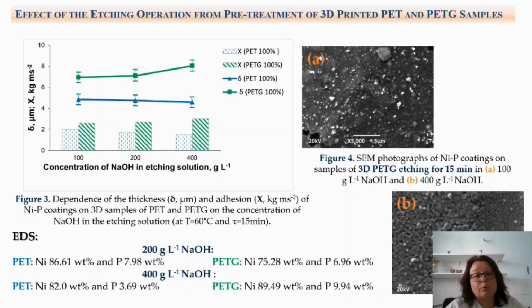When the sodium hydroxide concentration was increased to 400 gram per liter, the surface was more deeply pitted, leading to better surface catalysis and resulting in higher chemical reaction rates and a more intense deposition of electrolytes, nickel, phosphorus, and hydrogen. The porous structures indicated that hydrogen was released locally on preferential zones such as the largest palladium grains, forming pores.